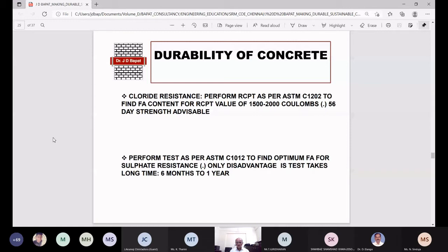Now, perform RCPT as per ASTM C1202. So I indicated two things over there. One is RCPT. What is the meaning of RCPT? It is rapid chloride penetration test. To be very correct, it is rapid chloride ion penetration test, RCPT, as per ASTM C1202, to find fly ash content for RCPT value. Now what is the RCPT value? Acceptable RCPT value for good chloride resistance is 1500 to 2000 coulombs. And then, as I have already told you earlier, 56 days strength is always desirable, provided your structural engineer permits you.